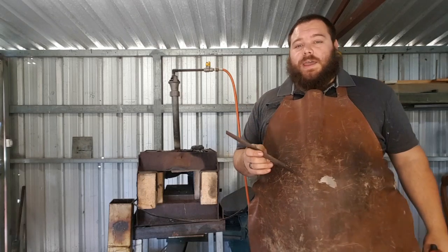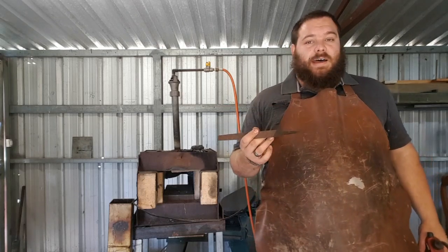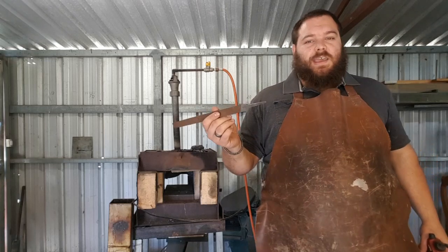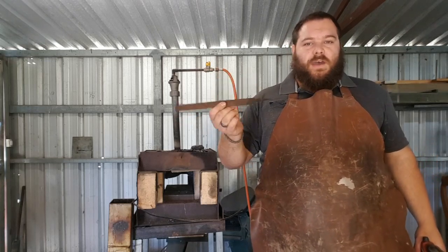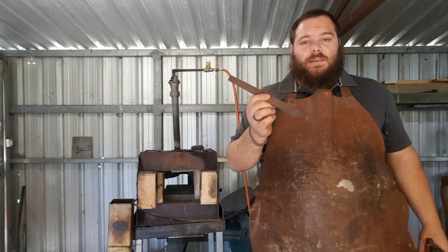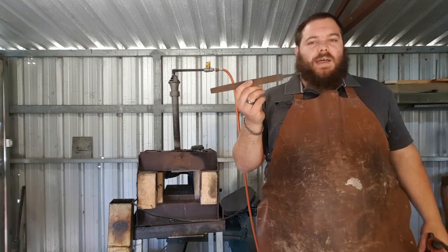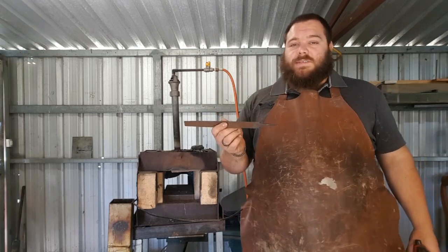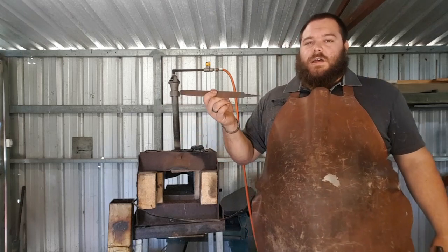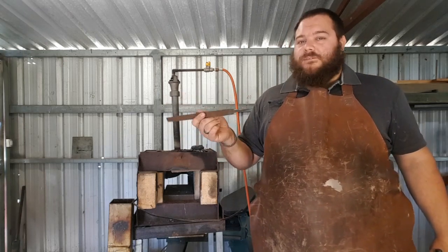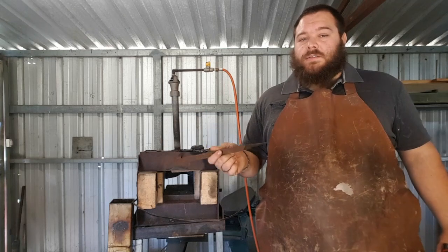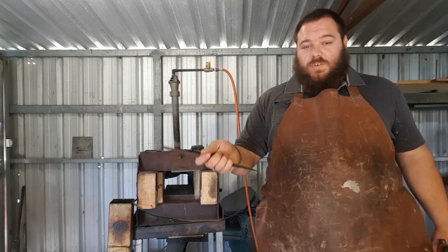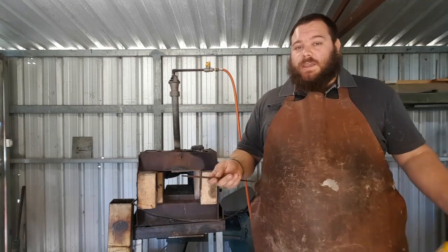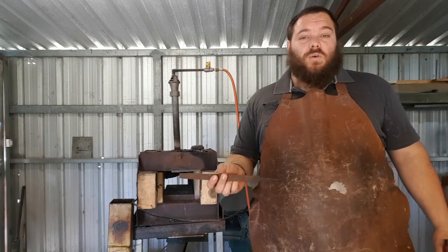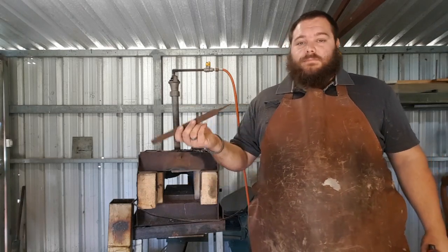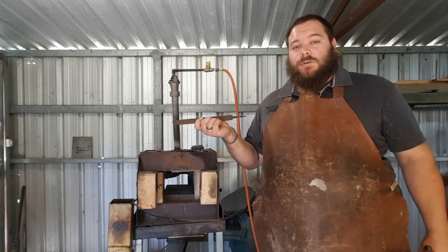Normally when I do a forged blade, I will normalize 3 times. In this case, because I'm just taking this file, which I've never manipulated before, it is hardened at the moment, but because I haven't done anything with it, I am going to do 1 normalization cycle for the purposes of this demonstration. If I was to normalize this or anneal this for stock removal with files or something like that, if I was making this by hand at home, I would probably do 2 or 3. But now I'll get onto that and I'll show you heating it up to critical temperature.